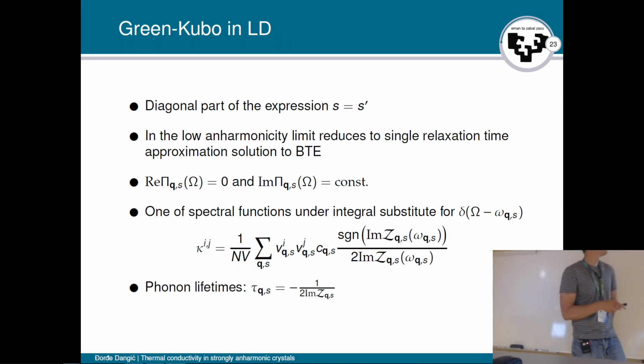And what we have found, and what we would expect, is that in the low anharmonicity limit, this expression reduces to the single relaxation time approximation, or the relaxation time approximation solution of the Boltzmann transport equation, basically the stuff that we got previously in the section on the Boltzmann transport equation.